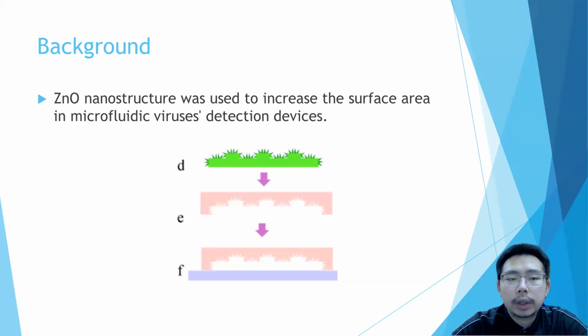This picture here illustrated how zinc oxide nanostructure were used on PDMS applications. First they synthesized zinc oxide on PDMS surface and then used it as a mold to create a microfluid device with increased surface area. Growing it on 3D printed resin parts has a similar idea as the PDMS application.